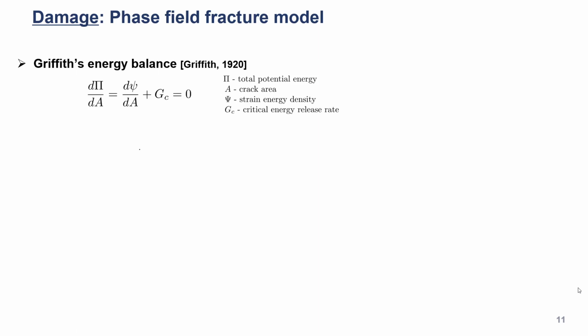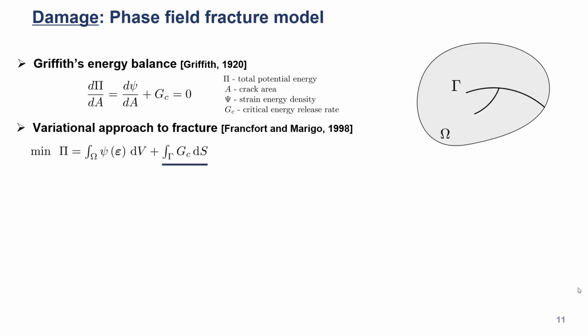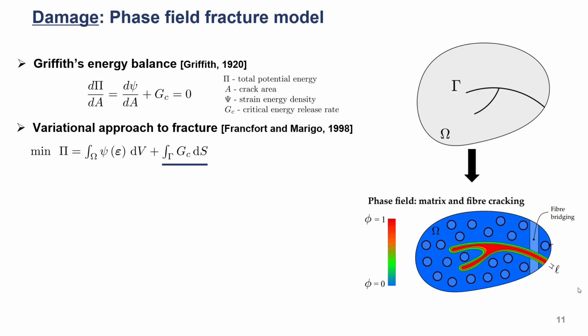The phase field model is basically a computational framework of Griffith's energy balance. One can write this equation into a variational form, basically integral expressions of the total potential energy. Minimizing this energy functional is actually very challenging because the sharp interface will introduce some numerical instabilities. However, we can use the phase field method, basically replacing the sharp interface by diffused regions. These diffused regions allow us to approximate the crack by a scalar field, like a damage variable from 0 to 1.